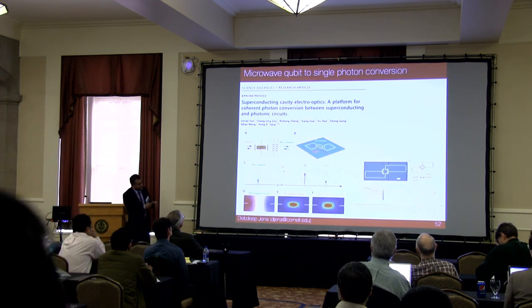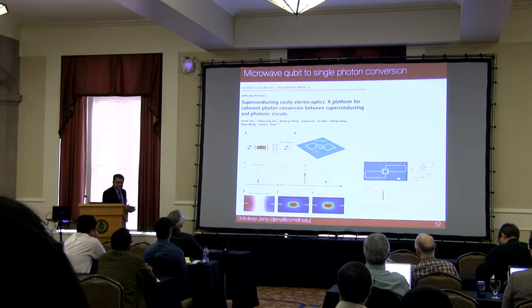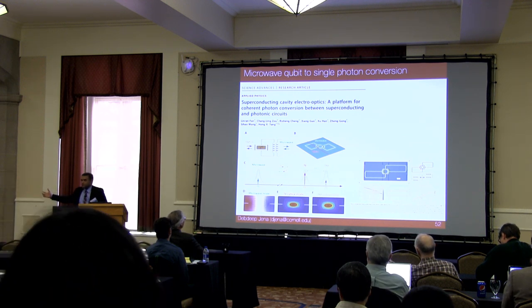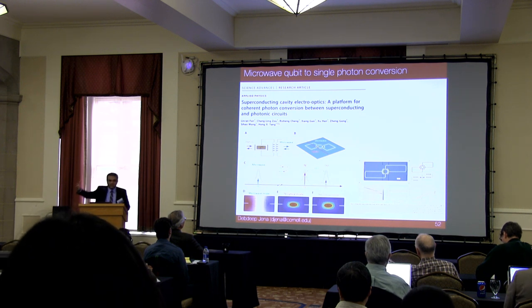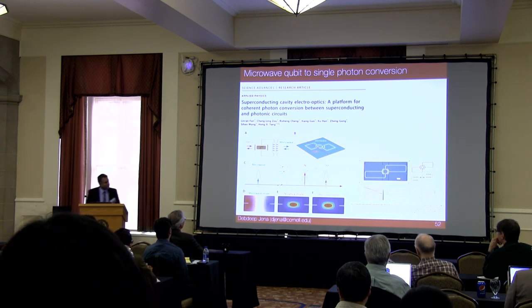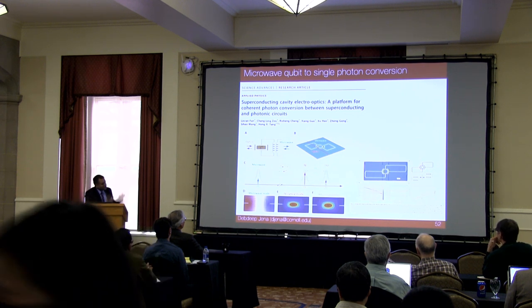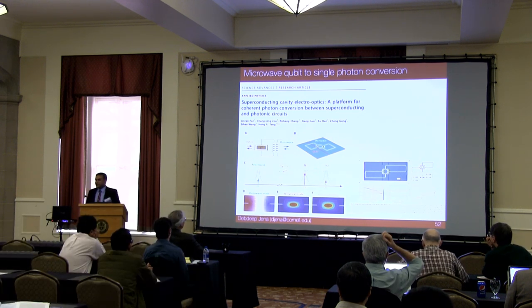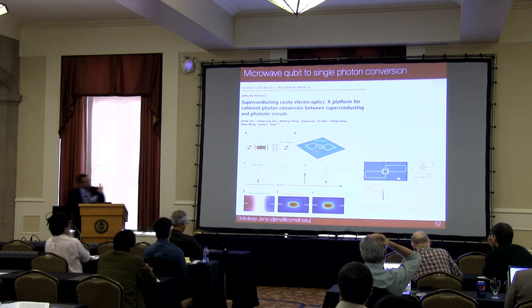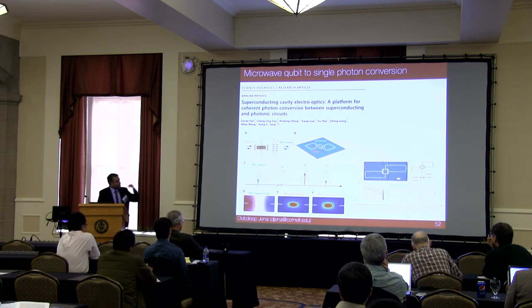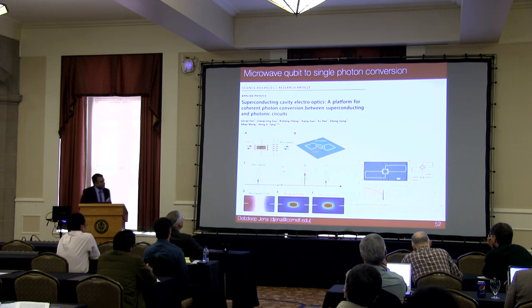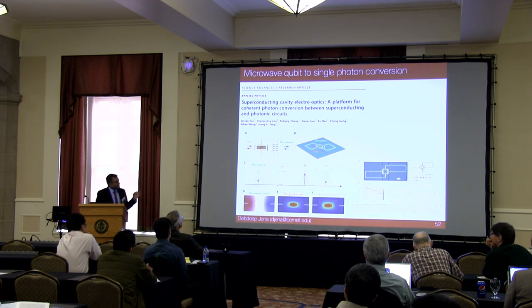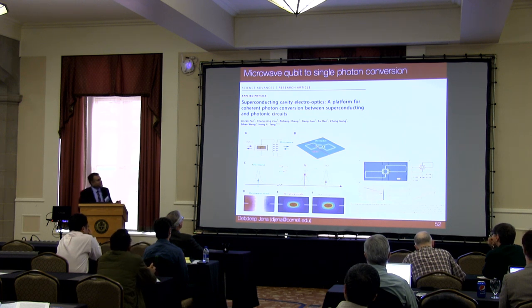paradigm for secure communications. Okay, so I'll end by saying that some of the new materials being looked at here are the standard quantum dot structure, but also things like hexagonal boron nitride. This has a very large band gap. It is also a nitride platform, so it can sit on all the electronics and the optical platform I mentioned. We are now able to grow these very rotationally aligned, high-quality boron nitride layers on top of very large wafers. And when we look at their emission properties, we can see that it has this anti-bunching effect, which shows that it's one photon being emitted at a time.